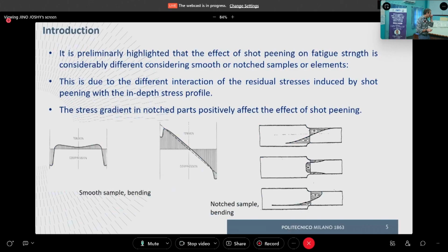And again, I have already said, maybe more than once, that the effect of shot peening is more relevant if we apply it to a notched part. And this is due to the stress gradient. And here we have another visual, graphical demonstration of this. What is represented here is a typical residual stress field in a smooth cylindrical bar, but it could also be different. It is compressive on the surface, along the external surface, and then at the core is tensile.